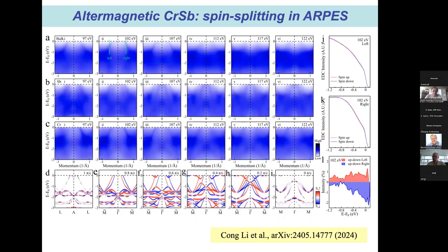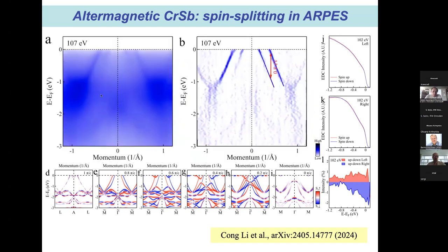I'll just show you one result from our colleagues from Sweden with whom we worked, which is ARPES, because ARPES is in QMatS an important technique. They did ARPES on chromium antimonide. This is too much data. I'll just show you one cut at a certain energy, at a certain kz, where they measure that these bands are split by 0.8 electron volt. And that compares well with the DFT calculations. So that is a first measurement of the spin splitting in chromium antimonide.